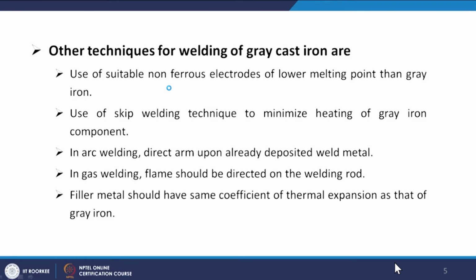Other techniques in welding of grey cast iron are the use of suitable non-ferrous electrodes of lower melting point than the grey cast iron, and the use of the skip welding technique to minimize the heating of the grey iron component. As we have seen, we can use the skipping method. In arc welding, direct the arc upon already deposited weld metal. In gas welding, the flame should be directed on the welding rod. It is not to be directed on the weld pool.